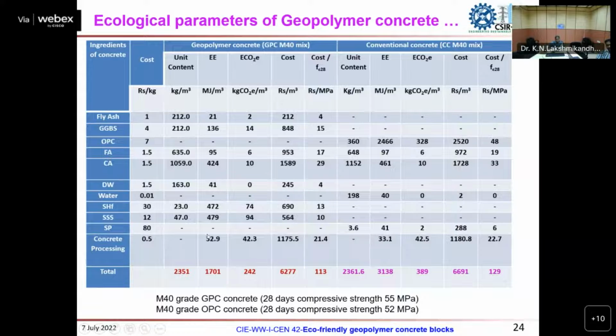A remarkable reduction in embodied energy and embodied CO2 is observed for the geopolymer based systems. So for M40, having 55 MPa for GPC and 52 MPa for OPC, these are the two quantities we have taken for comparison.